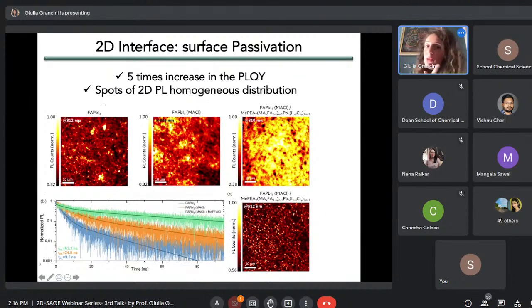I told you at the beginning that the 2D perovskites emit around 500 nanometers, no? So this is at 800, the emission with the 3D perovskites, which increases a lot. And then here is the emission mapped at 500 nanometers, showing the emission of the 2D perovskites, which indicates a very homogeneous distribution. The take-home message here is that such an increase in the photoluminescence indicates a reduction of the non-radiative losses of trapping at the surface. In other words, it indicates surface passivation, which is really the key to improve the lifetime of the carriers.